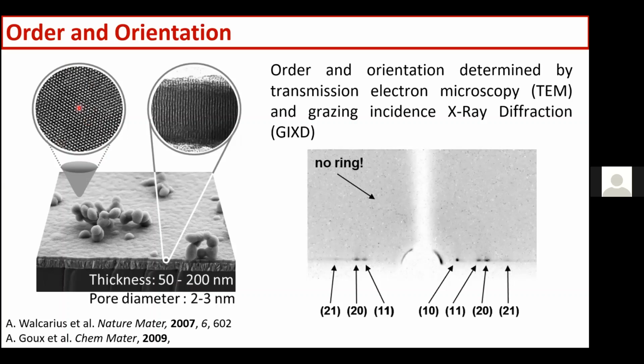And here you have a section of the film where you have the electrode here, and you can see that the pores are going all through the silica film thickness. So what is very important here is that by doing this electrochemical synthetic method, you have pores that are perpendicular to the electrode surface, so the electrode surface remains available for the analytes or probes to diffuse through the film and reach the electrode to be oxidized or reduced there.